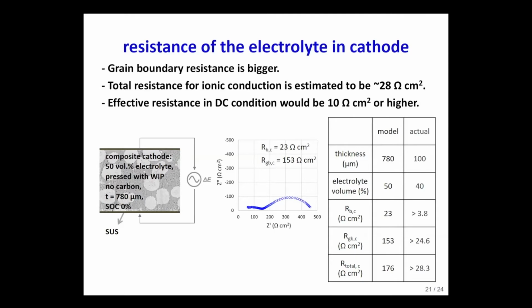The measured total resistance is about 170 ohm square centimeters. But after the adjustment, considering the actual cathode thickness and the electrolyte volume percent, it would be only about 28 ohm square centimeters. Since the whole current is not going to flow through the entire cathode, the effective resistance for the calculation of polarization is going to be about 10 ohm square centimeters. Actually, this number should be higher if we consider the increase in the tortuosity with decreasing the amount of electrolyte.